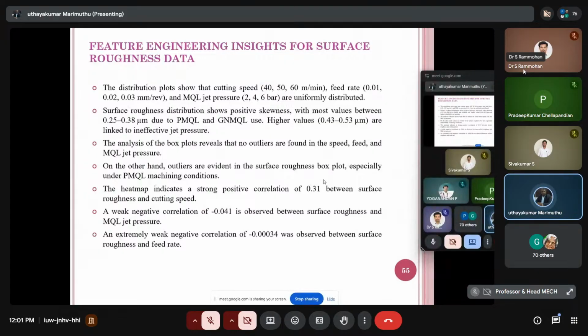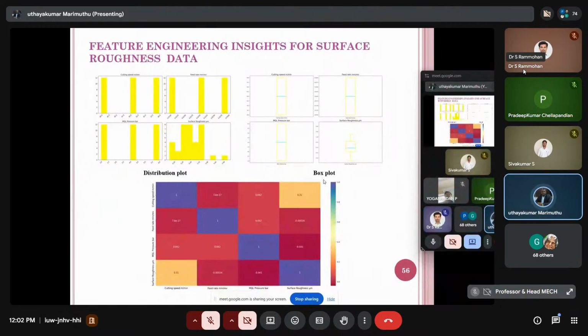The heat map indicates a positive correlation of 0.31 between surface roughness and cutting speed. A weak negative correlation of minus 0.041 is observed between surface roughness and MQL jet pressure. An extremely weak negative correlation of 0.000 is observed between surface roughness and feed rate. The appropriate evidence which we want to show by using the distribution plot and box plot is presented here. So this was reported there.